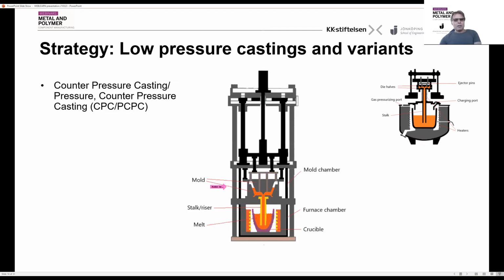There is another way you can do, and that is the counter pressure casting. And that is working in the same way. You have a system where you pressurize the furnace chamber, and you have a hermetically sealed compartment around the actual die itself. So here you can pressurize the chamber, forcing the melt up the stalk, but you also can work with the super pressure in the furnace in the die compartment. And that means that with increased pressure in the die compartment, you can get a more quiescent type of fill during the process. Melt breakup is not as likely as it would be if you have vacuum, for instance. So that is one way of managing this as well.